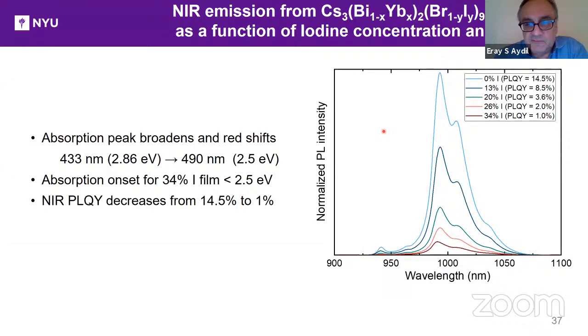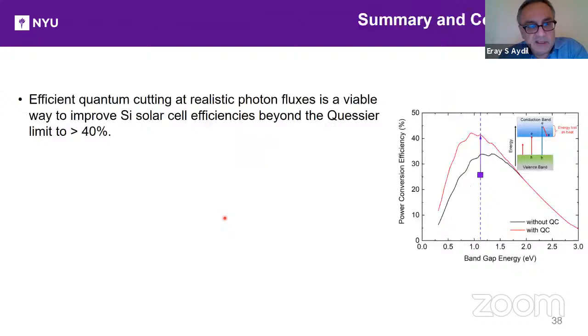So indeed, when one increases the iodine and shifts the band gap, the near-IR PLQY decreases from 14.5% to 1%, almost non-existent.